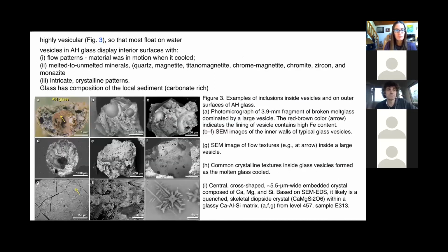A lot of this glass is very vesicular. Vesicularity means there are a lot of bubbles. So if you take this sediment and drop it into water, one way you can find these glasses is that many of them just float because of this vesicularity. You can see them on the surface of the water, take them, and analyze them. Looking closely at the optical image here, a lot of the internal surfaces of vesicles sometimes have a lining of iron oxide. In this case you can see a reddish color, which could be hematite or maghemite. Then we have examples of these SEM images.